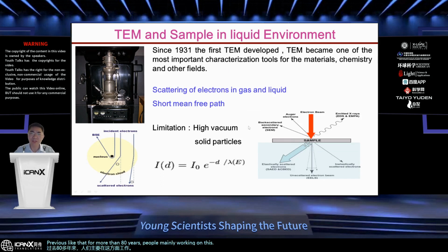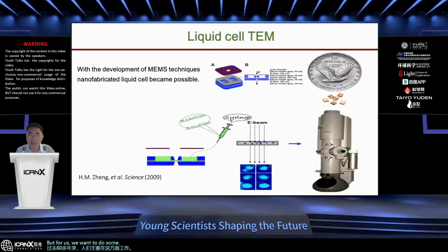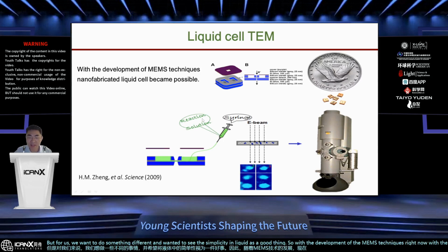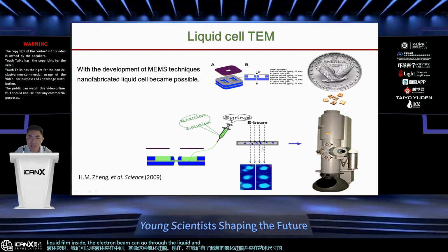But for us, we want to do something different. We want to see the samples in liquid. The good thing is that with the development of MEMS techniques, with a fabricated liquid cell, we can sandwich liquid between silicon nitride membranes. With an ultra thin silicon nitride membrane sandwiching a nanometer-thick liquid film, the electron beam can go through the liquid, and we can image particles inside the liquid.